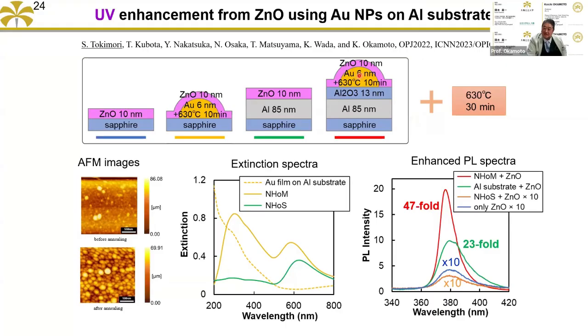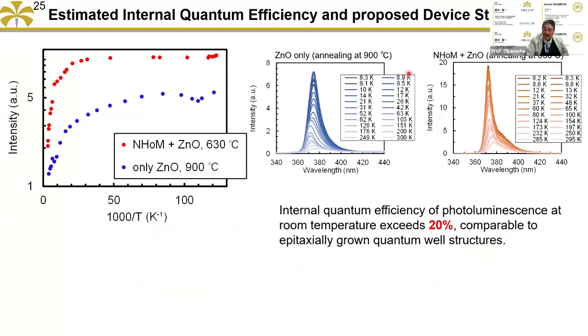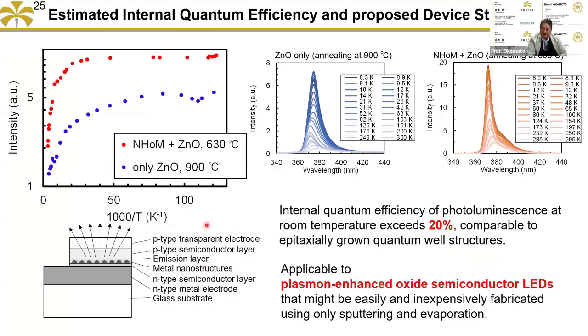But this structure is difficult to treat because the light emitter must be put on the metal nanoparticle. But in many cases, the emission material is already there, and we have to put the metal structure on the light emitting material. That's why we measure the temperature dependence to optimize the internal quantum efficiency of emission, and that's 20%. It's almost similar to the epitaxial growth quantum well structure. Then we believe that we can fabricate plasmon enhanced oxide semiconductor LEDs.